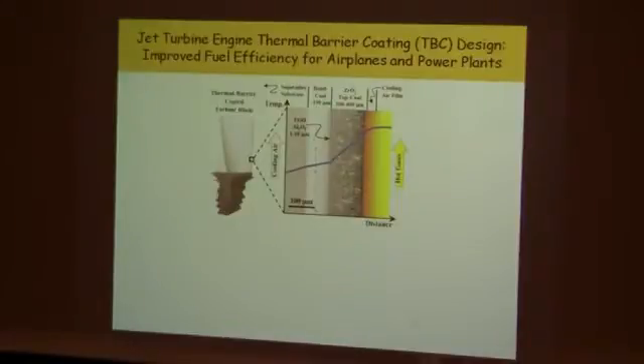Because what engineers figured out decades ago is that if you coat the metal with a ceramic coating, and it's not so trivial because it's complicated. This is the ceramic coating, made out of zirconia. But then you can't just put the zirconia directly onto the metal. You've got to put another metal alloy on it. There's a lot of stuff here. It's a really complicated system. But the fact is that they work really well.